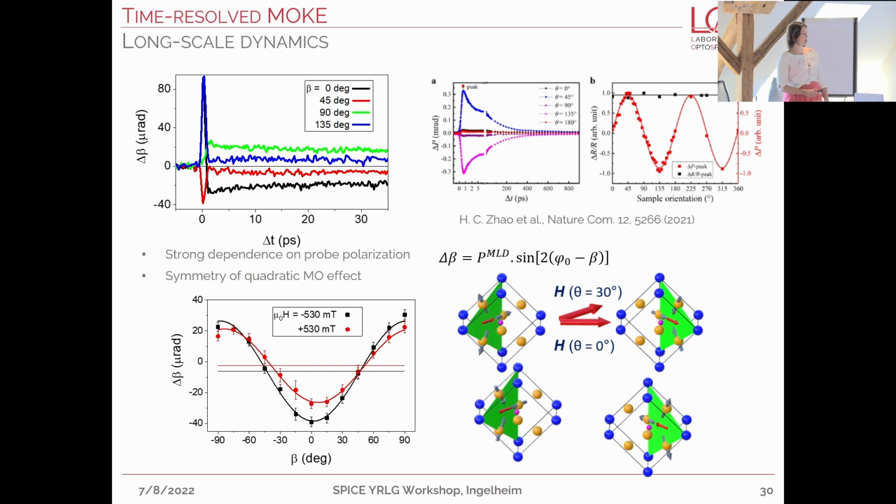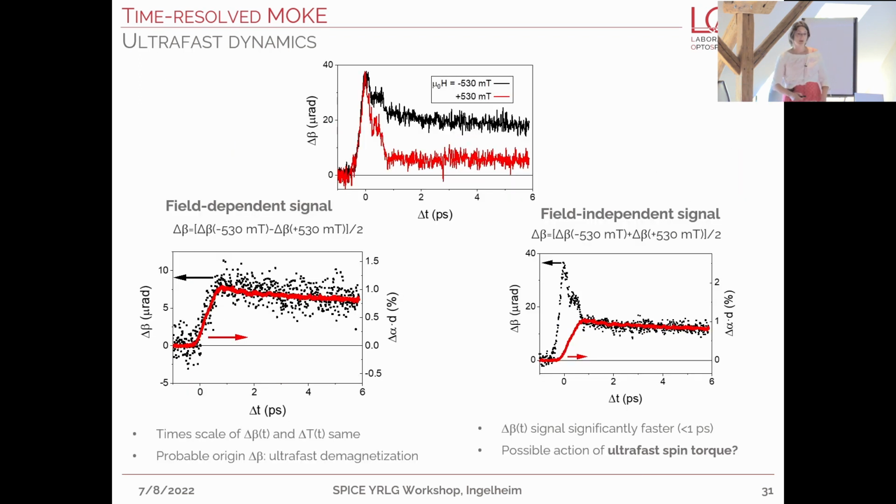But here, what was interesting is that this MOKE measurement enabled us to see a shift with external magnetic field. So it enabled us to see how we are repopulating the domains by adding external magnetic fields. We saw a shift that, in a normal ferromagnet, would correspond to the position of magnetization. In this case, the question is what is the magnetization? But anyway, we could see the shift as a function of external magnetic field. But this was nice, but not so exciting.